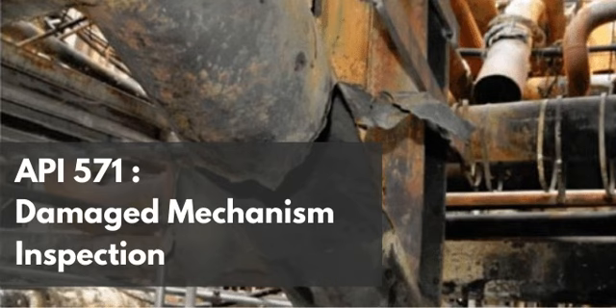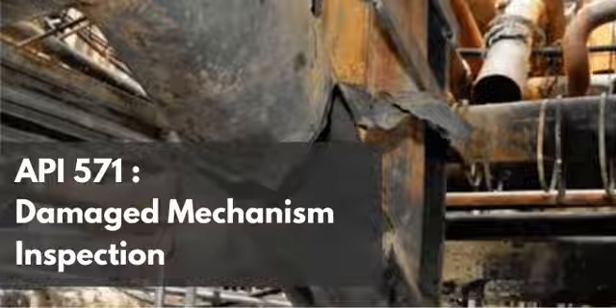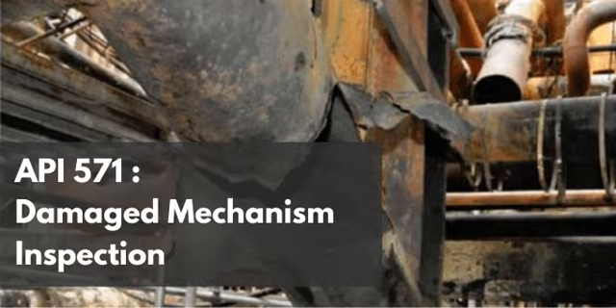When we look at how this actually manifests visually on the metal surface, we see two primary behaviors on carbon steel and low alloy steels. Yes, the damage profiles are very distinct. The material primarily suffers from either uniform thinning in localized isolated locations, or it suffers from localized under-deposit attack. Okay, let's break those down. Let's look at the first one, uniform thinning in localized locations. I know that phrasing might sound like a bit of an oxymoron at first glance. Yeah, right. How can something be uniform but also localized? It sounds like saying it's completely covered in isolated spots.